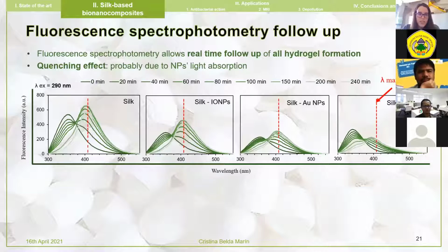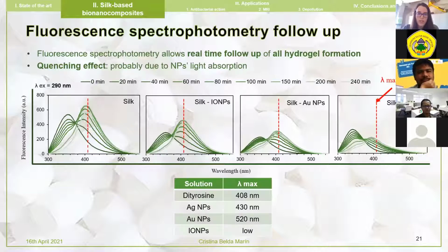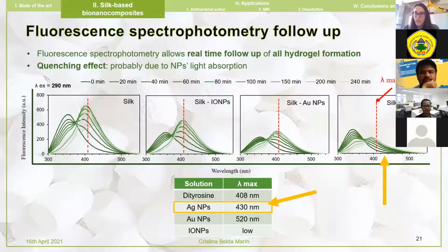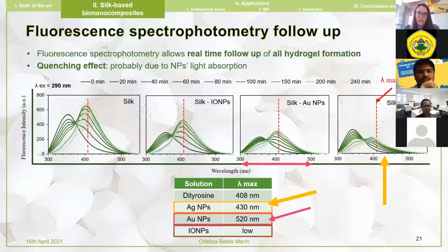So this lower intensity is called a quenching effect that's caused by the presence of nanoparticles, which is explained, for example, for silver nanoparticles. I remind you that the solution of silver nanoparticles absorbs light at 430 nanometers. That is very close to the peak of fluorescence of dityrosine, so it explains this reduction of intensity. Similar to gold nanoparticles, which have a maximum at 520, but have absorbance over the whole spectrum. And a lower effect is seen for iron oxide nanoparticles, as the absorption of light is much lower than the other two.